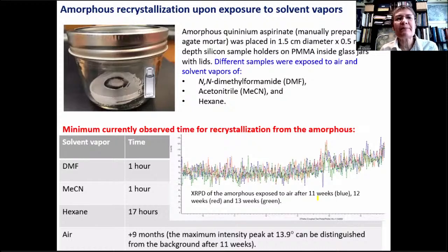So then the other experiment that we did is to expose those amorphous phases to vapors of various solvents: dimethylformamide, acetonitrile, and hexane. And we can see that using dimethylformamide and acetonitrile, in 1 hour, the amorphous becomes fully crystalline. I'm going to show the diffraction data in another slide. Hexane took a little bit longer, but here I have to measure this again because I had to go home in the middle of the measurement. So this is not the final number there.